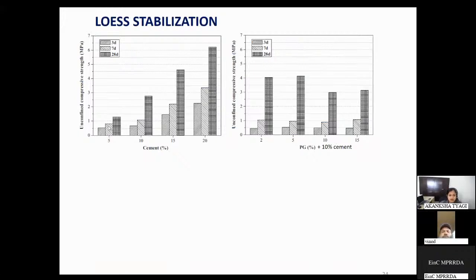What they see is, if you look at the early strength, this is 3 day, 7 day, and 28 day. Again, 3 day, 7 day, 28 day. If you look at 3 day and 7 day strength, adding more phosphogypsum decreases the early strength. If you look at 28 day strength, using 2% phosphogypsum, the strength is quite high compared to using only 5% cement. And using 5% phosphogypsum plus 10% cement, it is actually higher than with only 10% cement. But adding 10% and 15% phosphogypsum, the strength lowered again for loess type of soil.